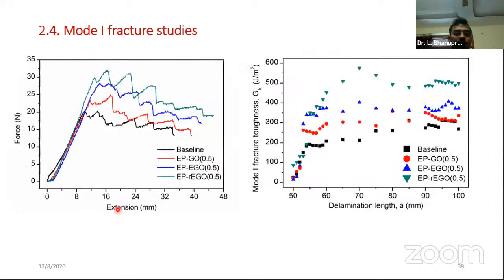And the extension, that is the delamination length, that is the crack length, against the mode 1 fracture toughness is drawn here. This is a baseline, and very good improvement can be noticed with reduced GO.